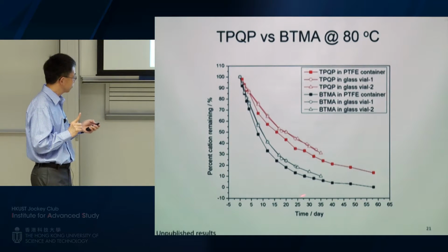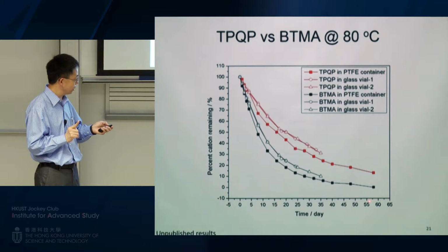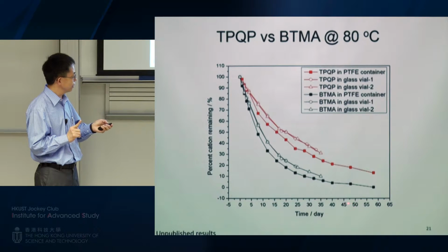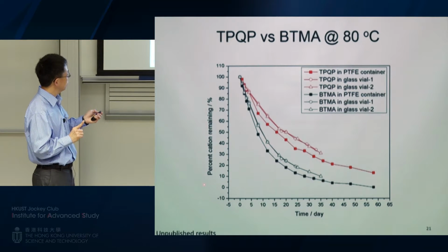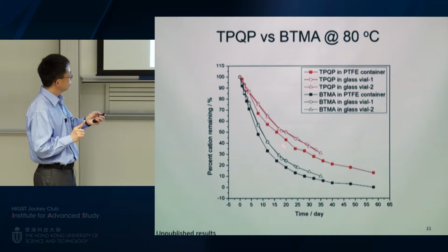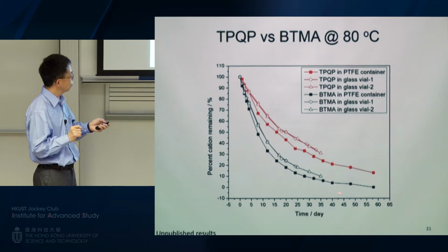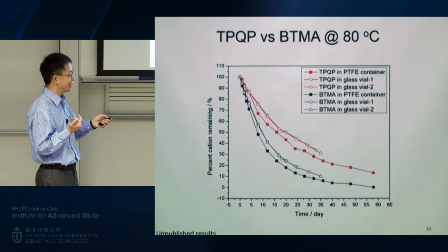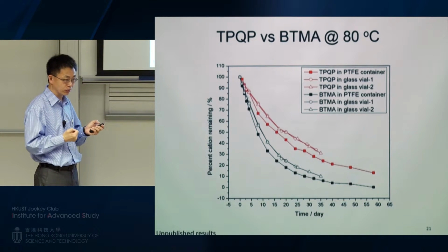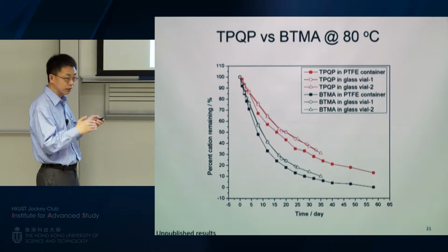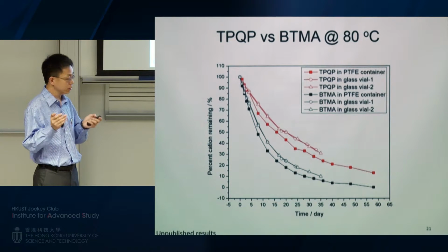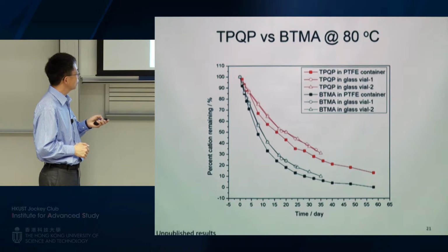So this is what we found. This is the horizontal axis, this is the time, the organic cation inside the solution, and this is the percentage of the cation remaining. So the red is our quaternary phosphonium with 9 methoxy groups. And this is the quaternary ammonium, the benchmark, the nitrogen one. This is the phosphorus one. So you can see, indeed, this one is more stable than this one. You may think this is of very little difference, but this is a very aggressive test. So if you take the methanol away, the difference will become bigger. But nonetheless, it's more stable.